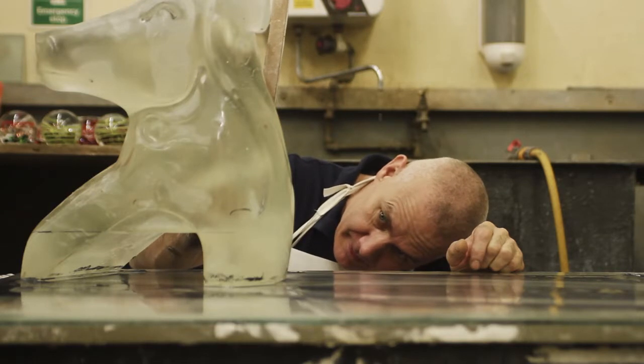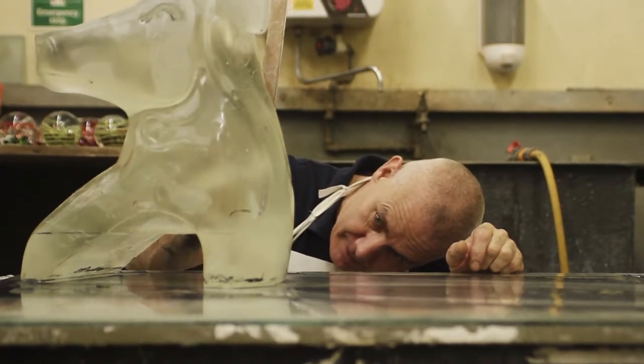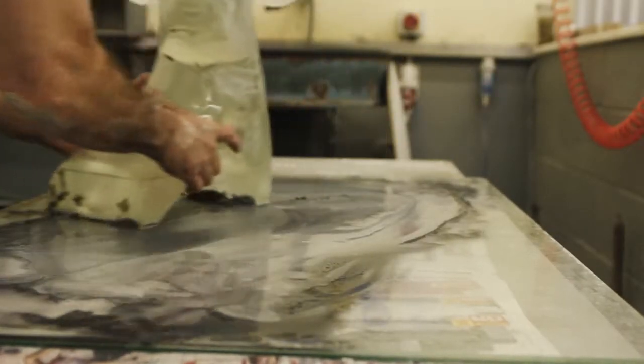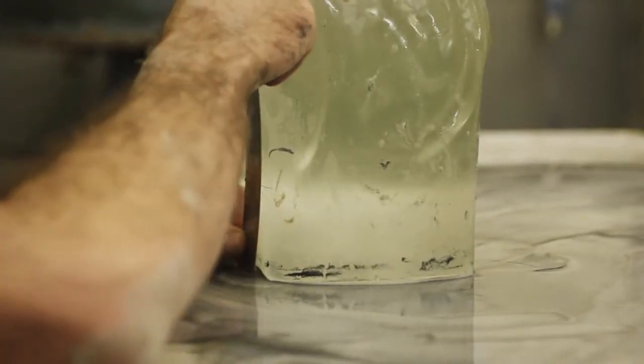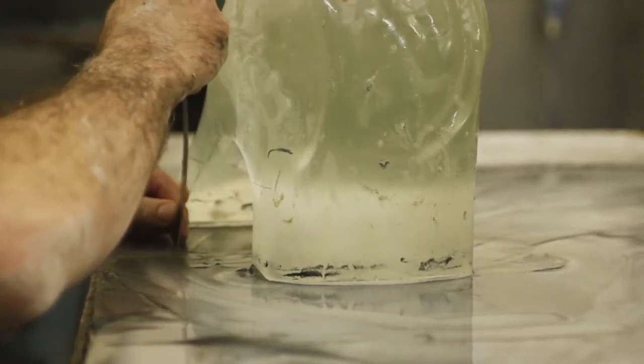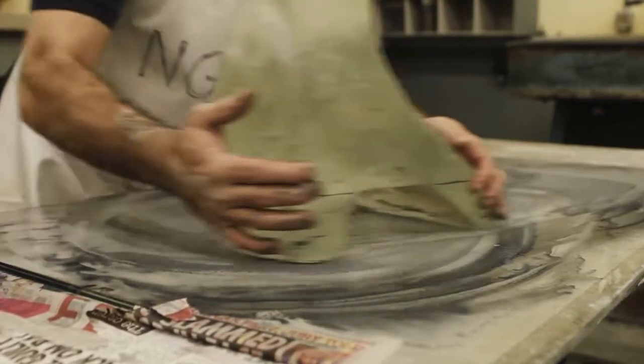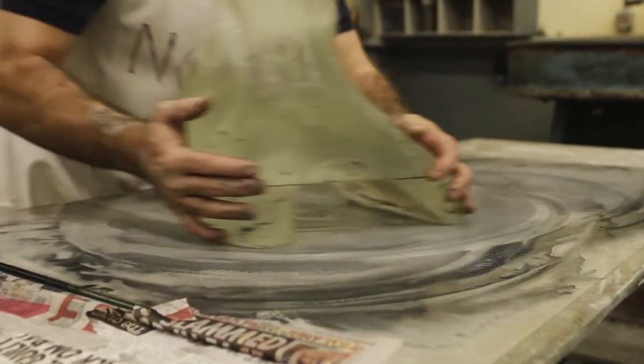It doesn't take as long as one might imagine, because the piece is quite heavy, so it almost grinds itself down. So it takes about half an hour, 45 minutes, and we go 60 grit, and then quite quickly we move to finer grit and take it up to 220. It goes to be acid polished.